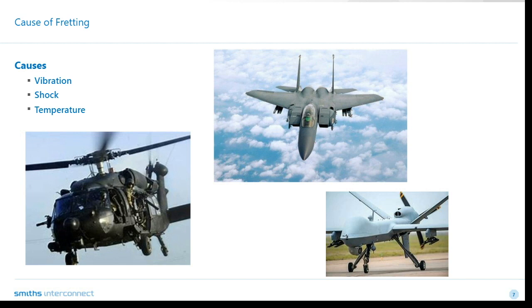Another common cause of fretting is repeated thermal cycles from cold to hot. As the contact surfaces are heated and cooled, the materials expand and contract, causing micromotions. Power cycling can also contribute. As the power is cycled on and off, the metals heat and cool. High temperatures also increase the rate at which non-noble metals oxidize, nickel, for example. Lastly, repeated mechanical shocks can also induce micromotions in electrical contacts and lead to failure. The mean time between failure may be greater in this case, but all attempts should be made to prevent any of these factors from occurring at the contact surfaces.